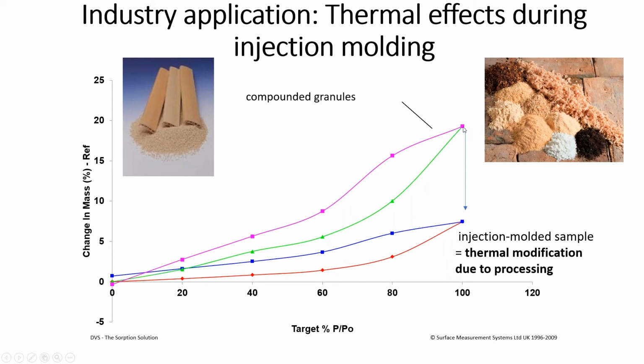It experiences a thermal history or a thermal treatment in the machine, and we measured how strongly the thermal treatment during processing is affecting the sorption behavior, and that's quite an impressive change in the properties. So thermal modification due to processing, that's something that we were able to show. This was just one experiment we did to discuss the issue with an industry partner.